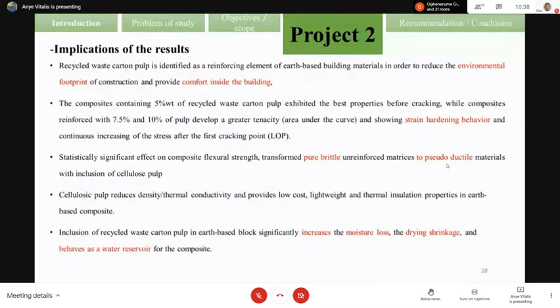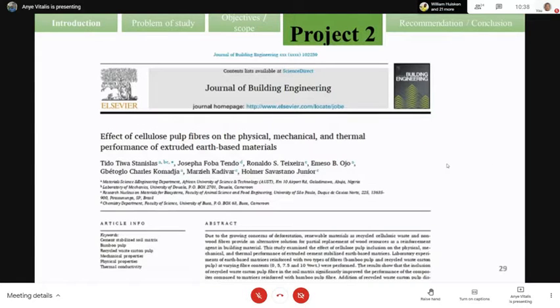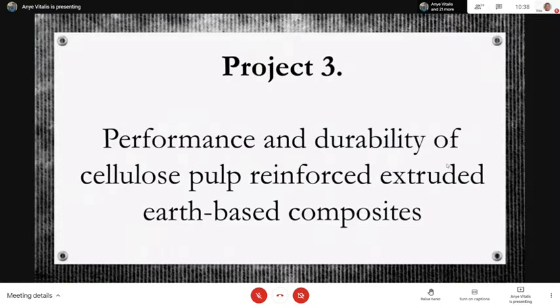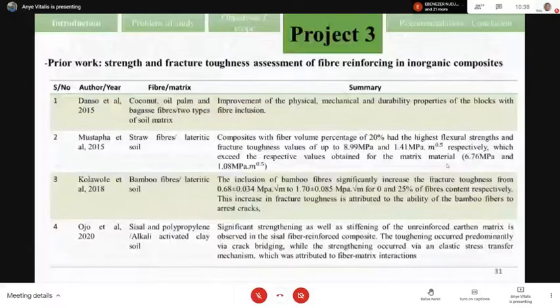Also, the fiber has a negative effect in that it absorbs more water. It also increases the dry shrinkage, although the value of the dry shrinkage is significantly low compared to the maximum value required, which is around 8%. So now this is the paper we have published from the second project in the Journal of Building Engineering: performance and durability of cellulose fiber reinforced earth-based material. So what is the previous work we have done?